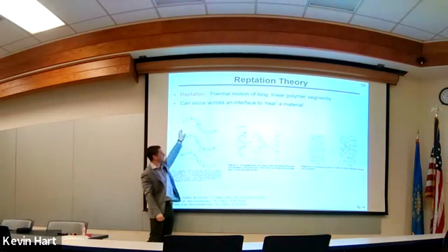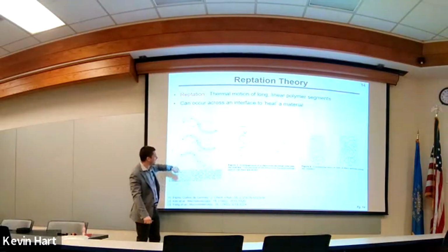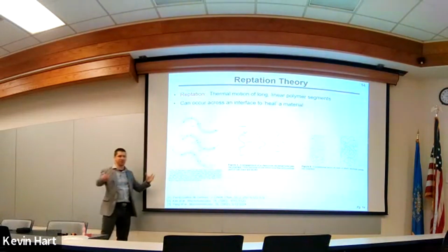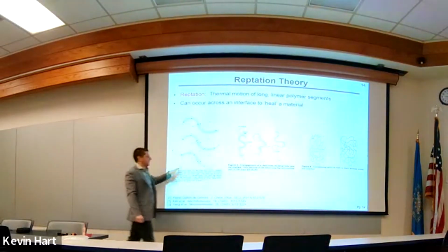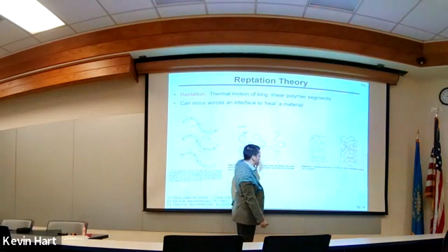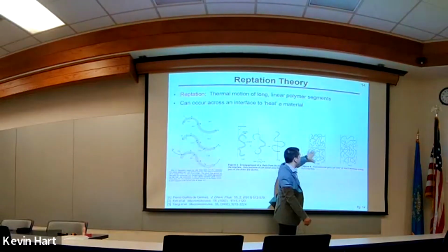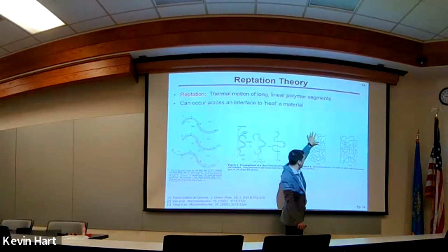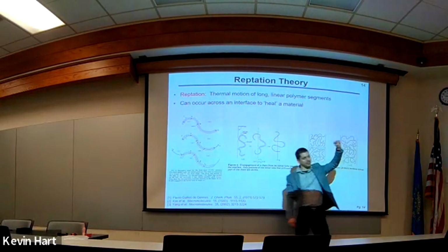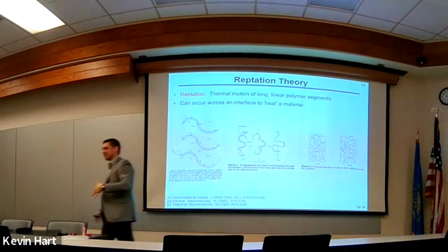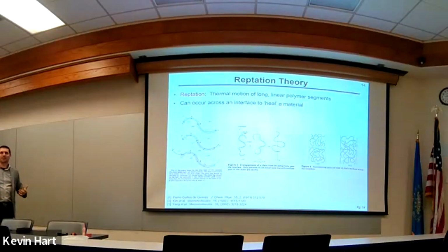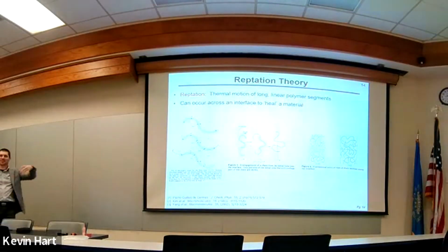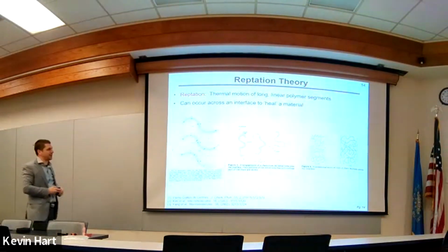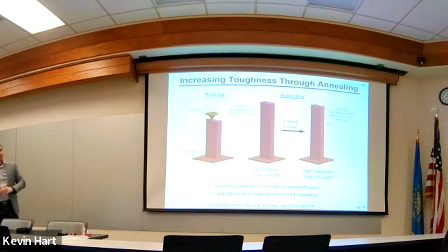This idea that polymers live in these tubes, these chains, and you can excite them out of these tubes using energy, temperature, UV, whatever, and get them to migrate and move. And the whole theory here is that, all right, we've got 2 layers of our 3D print. Layer number 1 has some polymer chains, layer number 2 has some polymer chains, and we're going to excite those polymer chains and get them to migrate over the interface using this reptation theory. It's the same base word as reptile, right? Snakes slither like reptiles. These are like snakes, polymer chains moving inside your material. It's the same general idea. All right, so that's reptation theory, and we'll come back to this a little bit later.